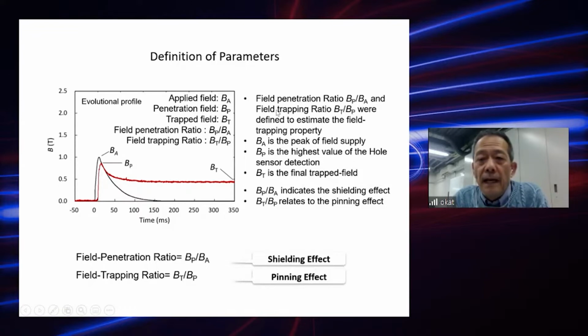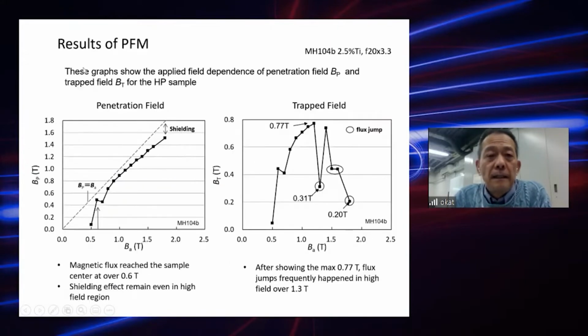At first, we must define the parameters to evaluate it: the field penetration ratio, BP over BA, and the field trapping ratio, BT over BP. BT, the final trapped field, and BP were defined to estimate the field trapping property. BA is the peak of the field supply, measured from the shunt resistor. BP is the highest value detected among all the sensors, corresponding to the peak. BT is the final trapped field like this. BP over BA indicates the shielding effect, and BT over BP corresponds to the pinning effect. These are very important parameters.